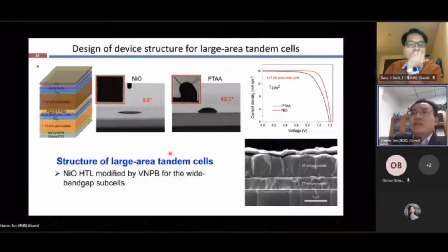So the next step, we try to fabricate larger area tandem devices. Another challenge is the deposition of uniform wide band gap perovskite on the traditionally used polymer-based hole transport layer, because the surface wetting is not good and the contact angle is very large.